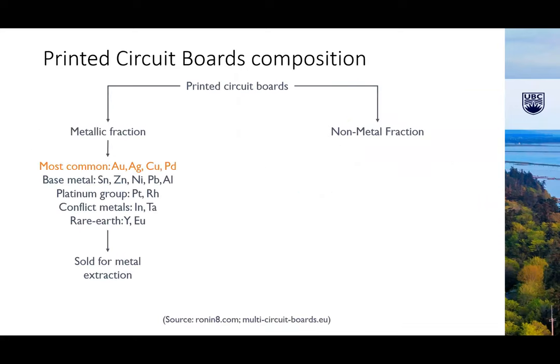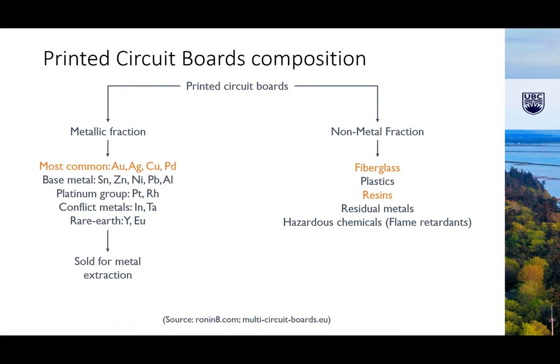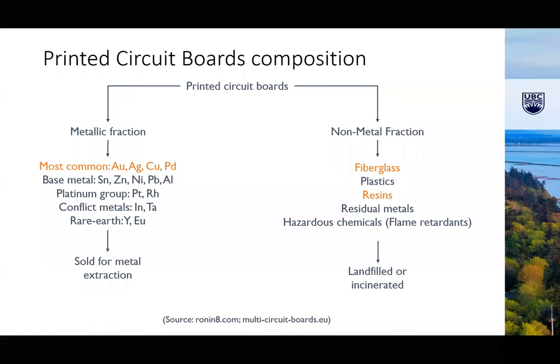So looking at the composition, we have metallic fractions: base metals, precious metals, rare earths. Usually when we recycle, these are extracted and sold for metal extraction. When we look at the non-metal fraction, on the other hand, what we have left over is fiberglass, plastics, resin, and residual metals, if the separation at the stage of metal extraction is not efficient. And obviously, all these plastic resins and fiberglass are coated with flame retardant. So this is what we are left with after we get the metals out. And in the normal scenario, landfill or incineration is the fate of this material.